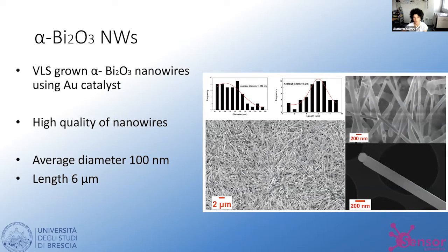Then we have tried also to prepare other P-type material like bismuth oxide, which is not so used as a gas sensor material. And even in this case, the best catalyst was gold. And we can see here the morphology of these nanowires, and we can see that in this case the diameter is much higher compared to the other oxide. Then we have a diameter around 100 nanometers and a very long length, 6 microns in length. While we can see that at the top of the nanowire we have still the presence of the gold catalyst.